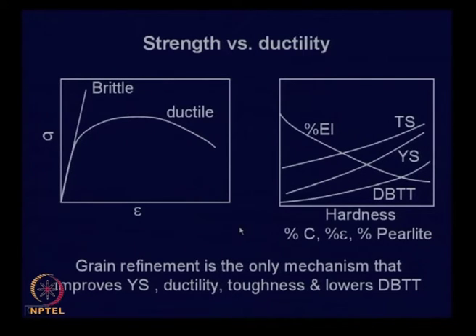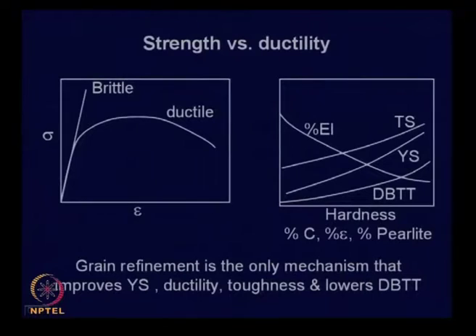Now, with most of these strengthening mechanisms, if you try to increase the strength of a crystal, what effect does it have on the ductility? If you recollect our initial stress strain plots, normally brittle materials are those which break even before plastic deformation occurs. So, a brittle material's stress strain plot will be virtually linear, and here it breaks. In fact, if you have a fully hardened steel wire, hardened to martensite, and you find its stress strain diagram, you will find that before it deforms, it breaks. But the same steel wire, if you anneal it and make it ductile, will exhibit this kind of stress strain behavior.